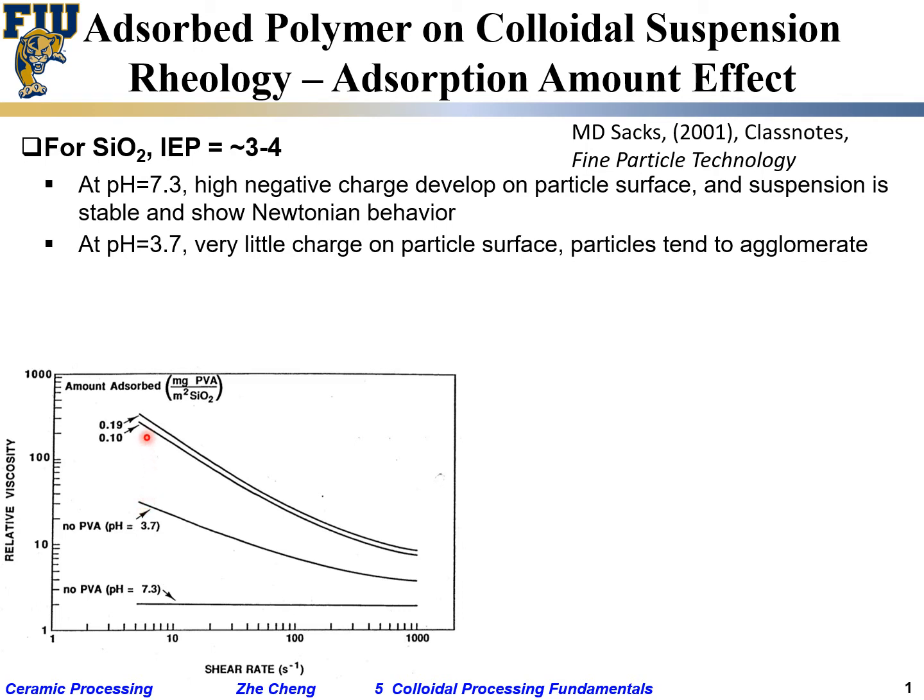And then when I have higher, remember this is for amount adsorbed what? Adsorbed PVA over your particles. As we increase the amount adsorbed, our viscosity actually becomes even higher. We do not yet have the so-called steric stabilization. We actually have the so-called bridging flocculation.